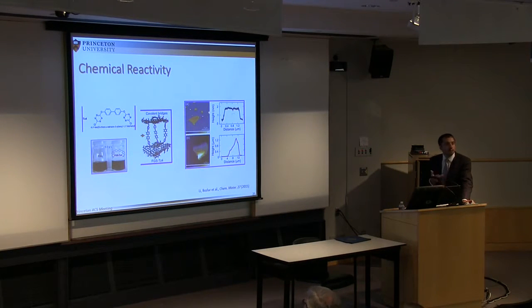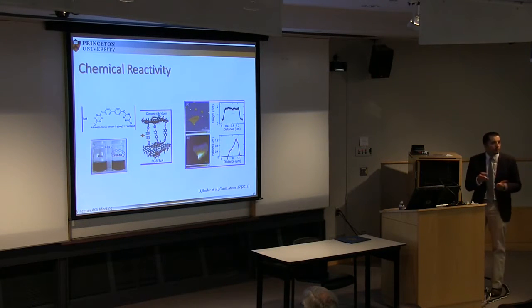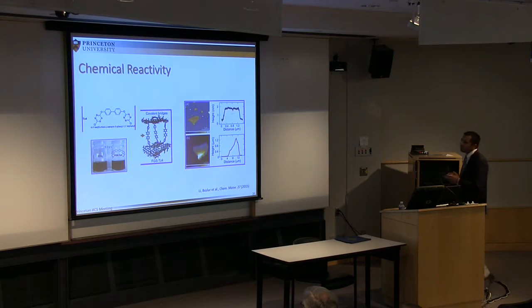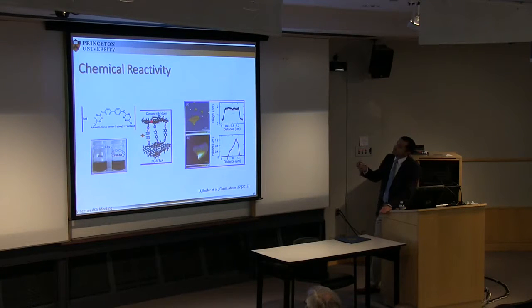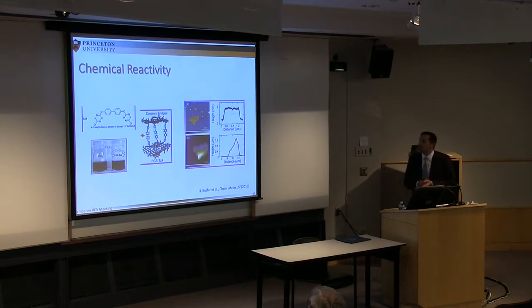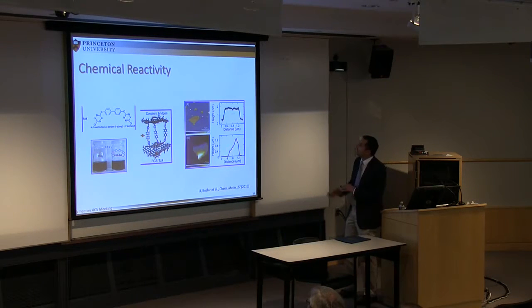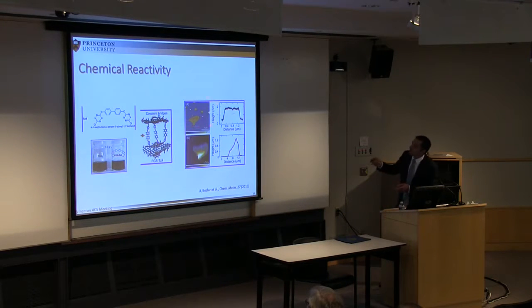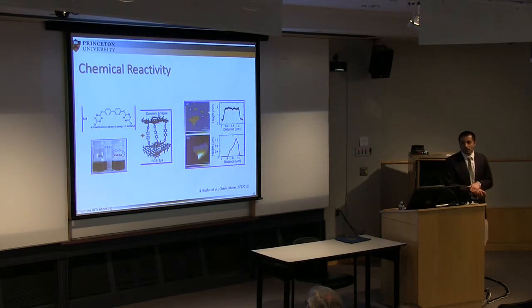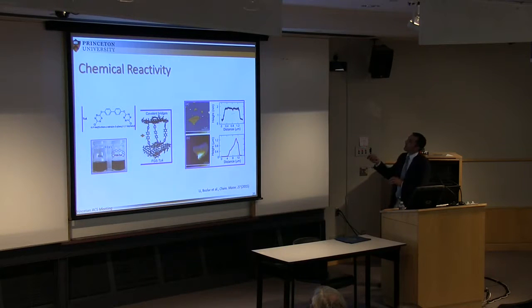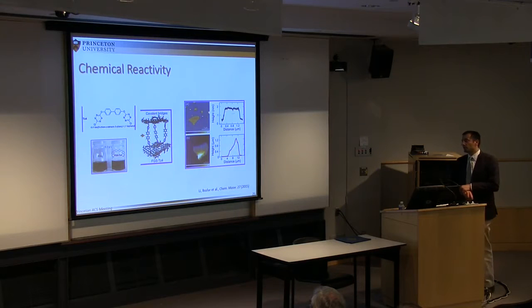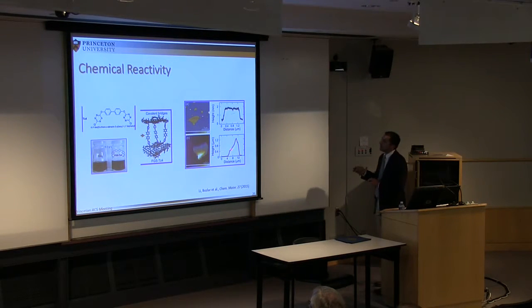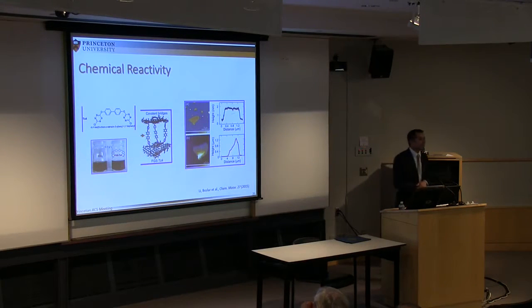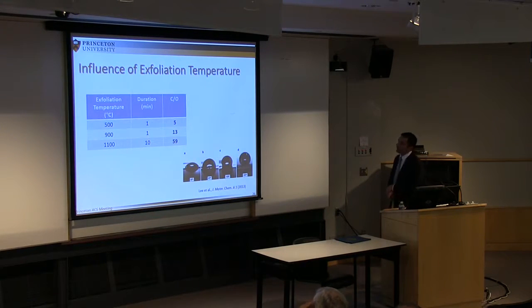So as I said, the fact that this material is highly defective and has a lot of functional groups is actually good in the sense that it allows you to do some chemistry with it. So we have been able to show that if you take this type of material, highly energetic with a lot of nitrogen in it, you can, through nucleophilic substitution, get rid of the chlorine bond here and attach it to two graphene layers and covalently link them. So we have demonstrated the covalent linkage using different techniques, and here AFM is one of them. If you look at here, in this case it's going to be graphene oxide, which has a carbon to oxygen ratio of 2. I will come to that in the next slide. You have a height of almost 1.8 nanometer that we are discussing. But as soon as you start doing something with it, you see we are reaching a height of a micron. So there was clearly something happening during the linkage.